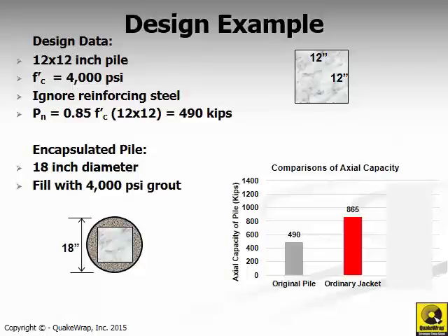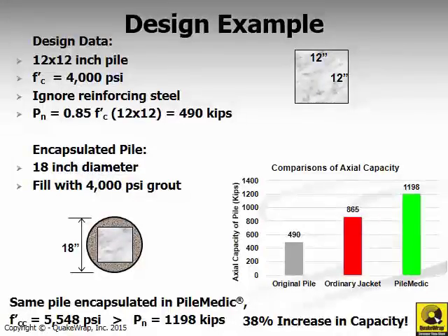And this gain in strength is primarily because of the increase in the cross-sectional area of the column and the added grout that we have introduced. On the other hand, if instead of an ordinary jacket, we use the same 18-inch diameter but make that jacket out of one of our PileMedic laminates, we can, for example, increase the strength of the f'c, or the compressive strength of the concrete, significantly to over 5,500 psi, both for the old concrete as well as the new grout.